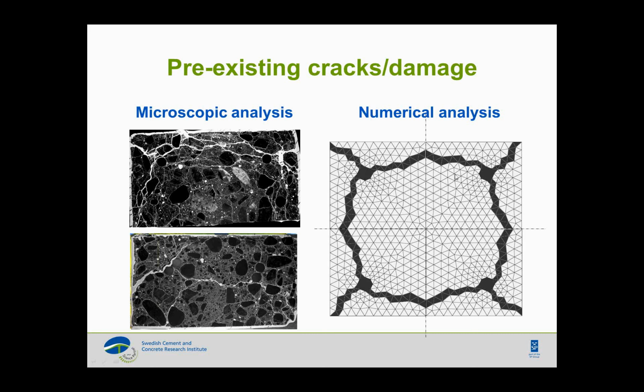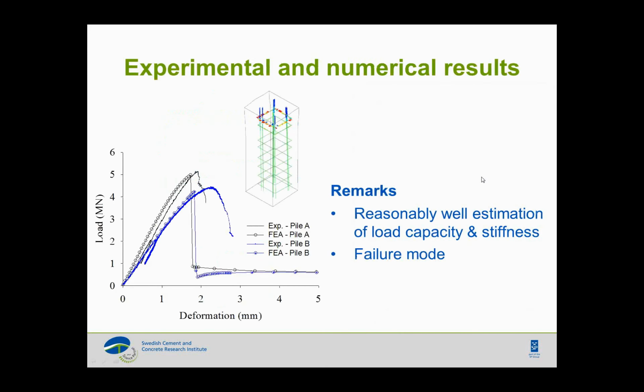We tested the piles in the lab with the displacement control regime with a rate of 0.3 millimeter per minute. Here we have the results in terms of the load and deformation for pile A and pile B. Here we have the experimental results, and here with the circles we have the simulation results. As we expected, we managed to capture the response with quite good agreement for the mildly damaged one. When it came to the severely damaged pile, there was less agreement, but at least we managed to capture quite well the stiffness in the beginning. I would also say that the load-bearing capacity of the pile was well estimated, but not the deformation at failure.